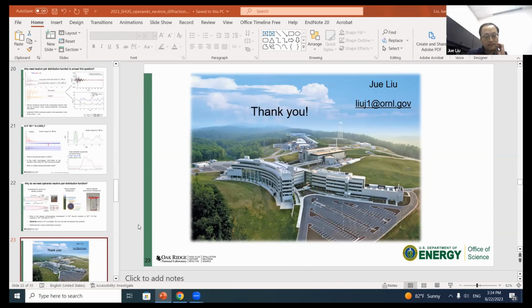Yeah, so for this in situ data, the data collection time can go down to about 30 seconds. But for the PDF side, in the in situ cell, we have not been successful so far. But I guess we probably need at least 5 to 10 minutes to get a reasonable PDF in an in situ configuration, if we achieve it. Yes.